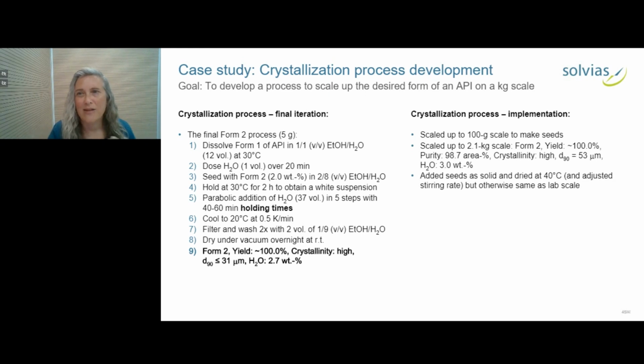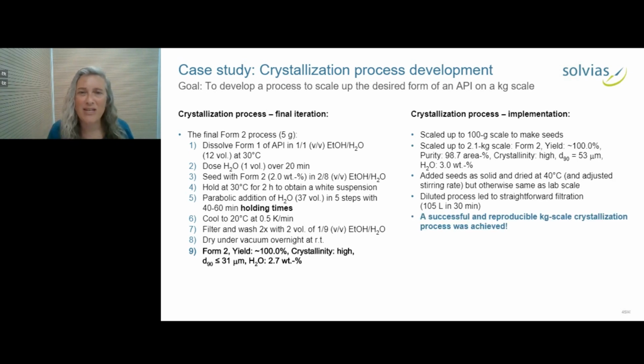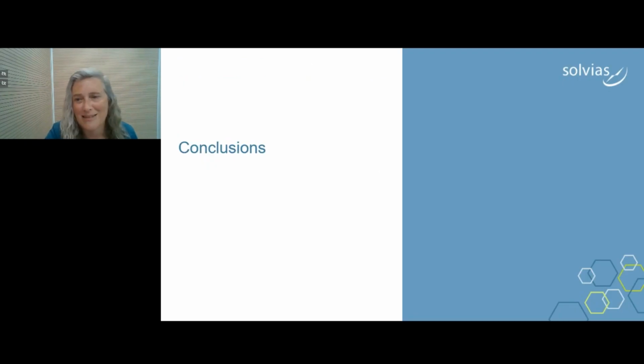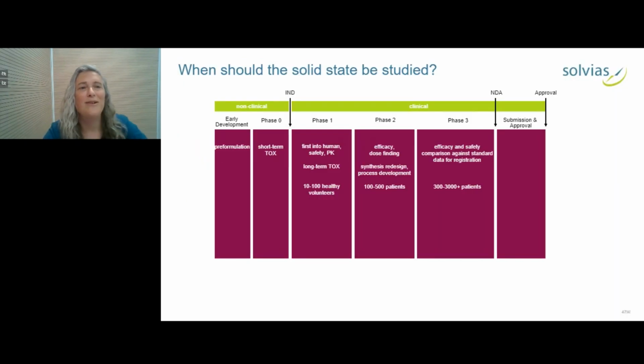We had to adjust the stirring rate so that the energy dissipation was matched, and there were some slight differences in the drying, but the process was good. We could filter it quite quickly, 105 liters in 30 minutes, and we achieved a successful and reproducible kilogram scale crystallization process. So to conclude, when should the solid state be studied?